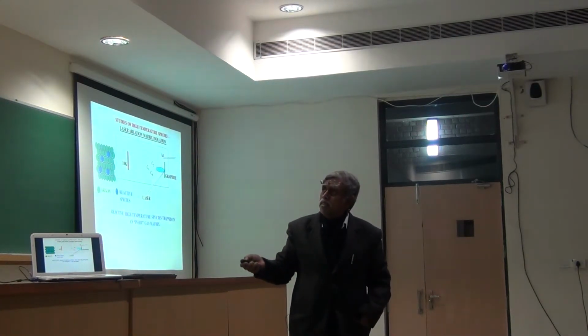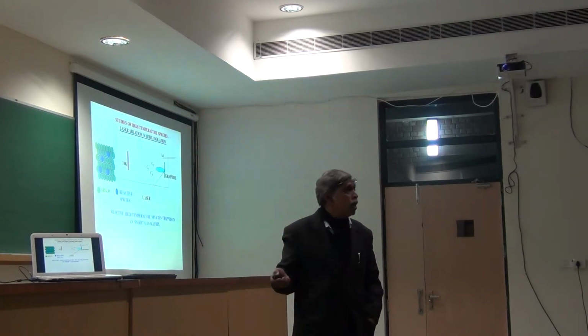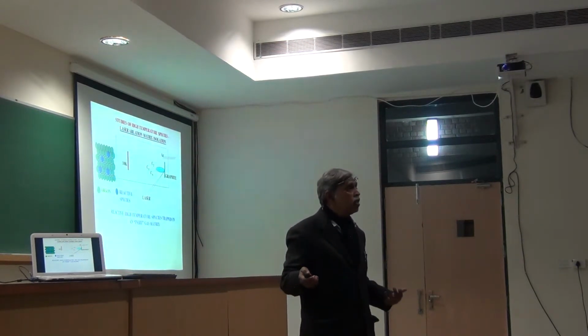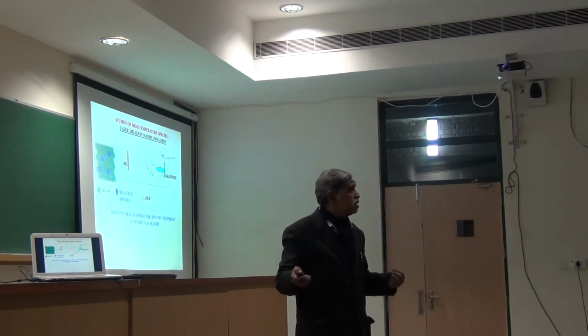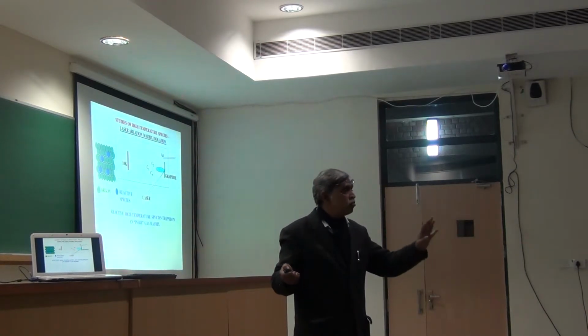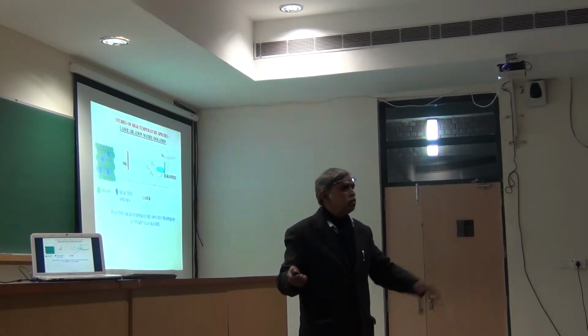Because R1 doesn't sit anywhere, it will get pumped off. But some of these target species might line up here, might line up here, but a good number of them will actually come and sit here along with R1, which if you now record the infrared spectrum, you will actually get the infrared spectrum of these various high temperature species that are now being trapped and caged in a low temperature sample.